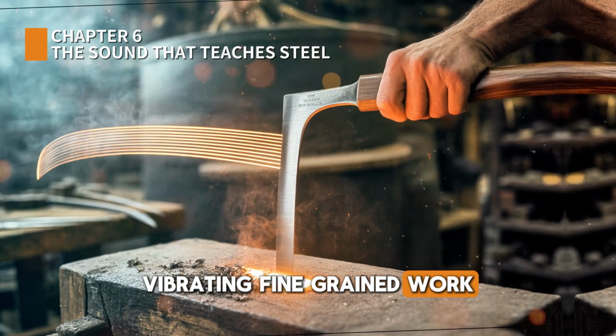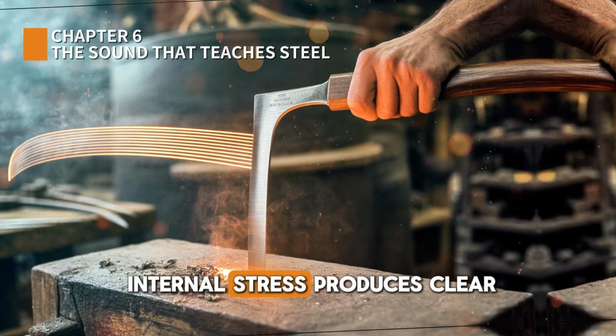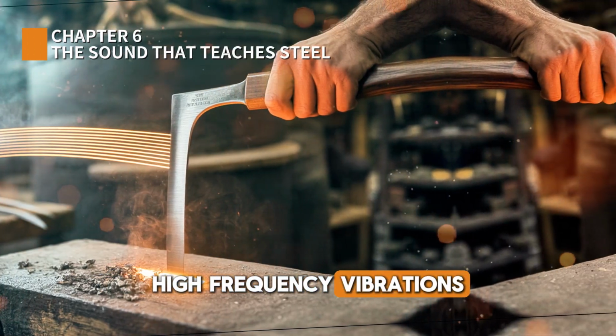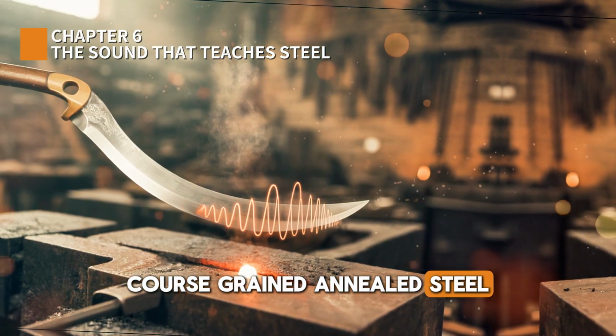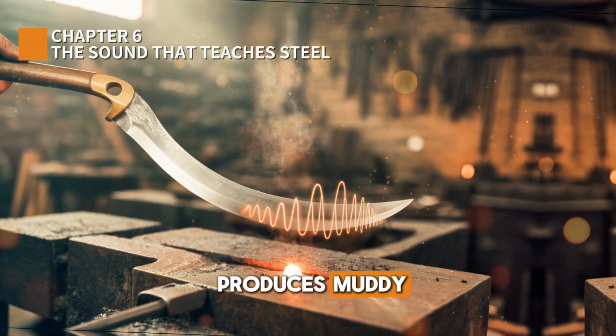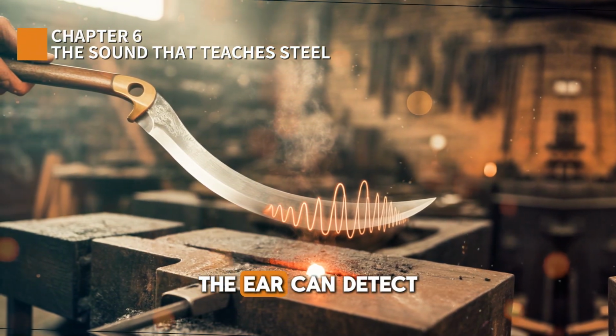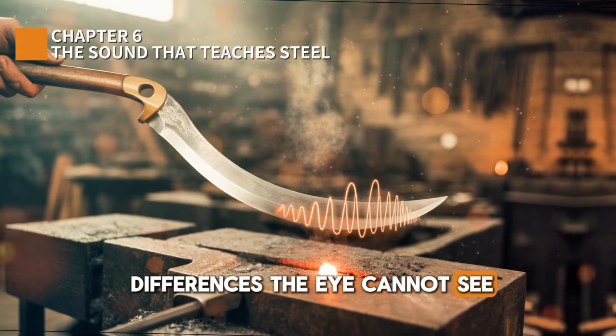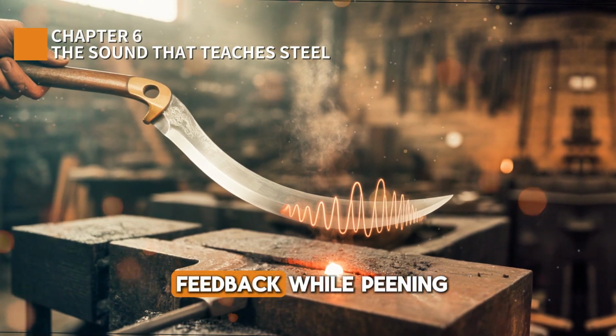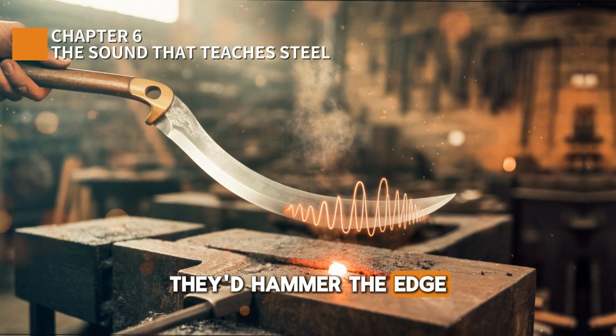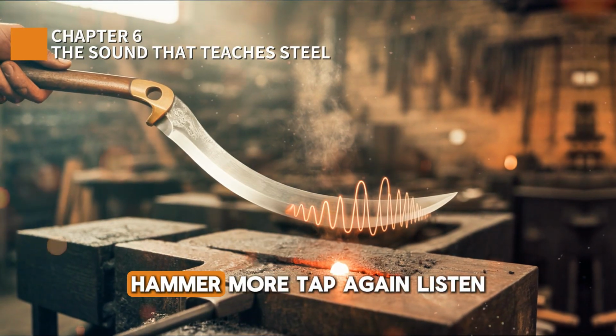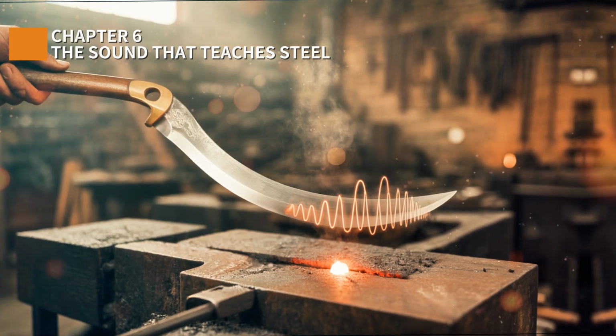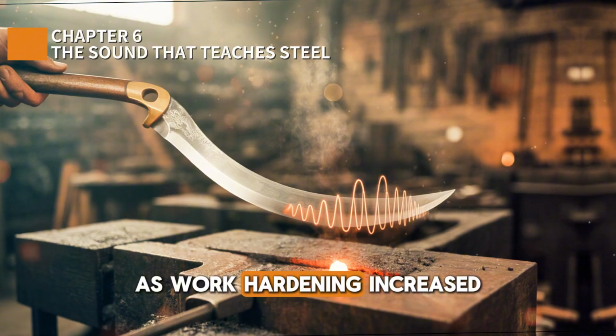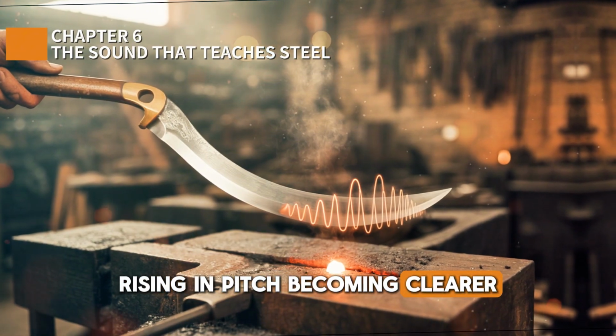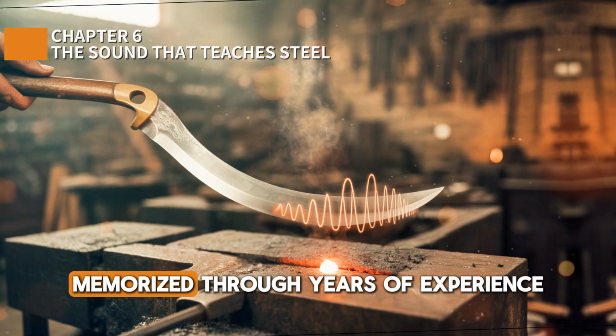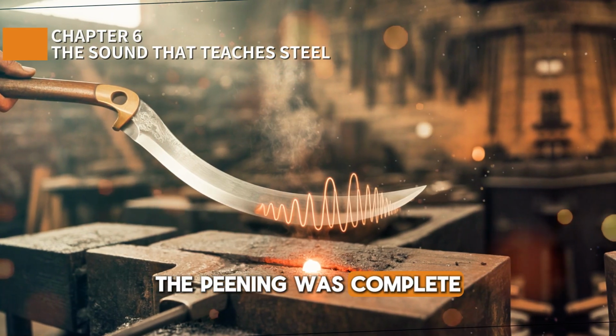Fine-grained, work-hardened steel with high internal stress produces clear, high-frequency vibrations. Coarse-grained, annealed steel with low internal stress produces muddy, low-frequency vibrations. The ear can detect differences the eye cannot see. Blacksmiths used this acoustic feedback while peening. They'd hammer the edge, tap it, listen. Hammer more, tap again, listen. The sound changed progressively as work hardening increased, rising in pitch, becoming clearer. When the sound reached the correct character memorized through years of experience, the peening was complete.